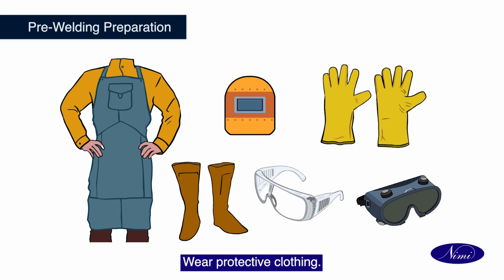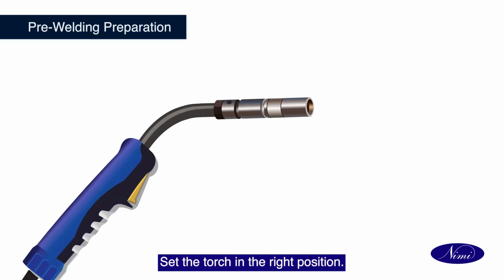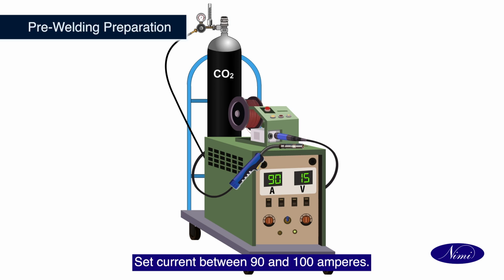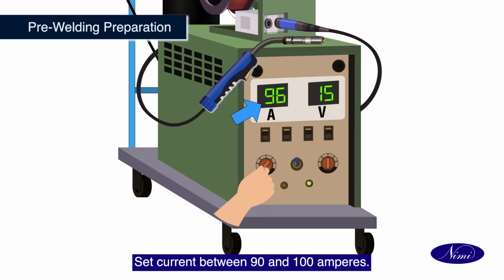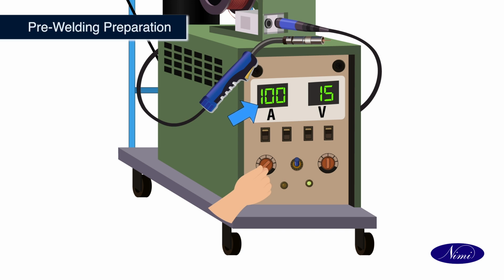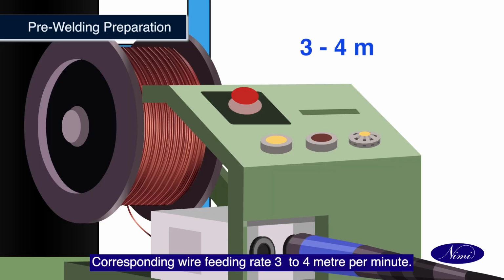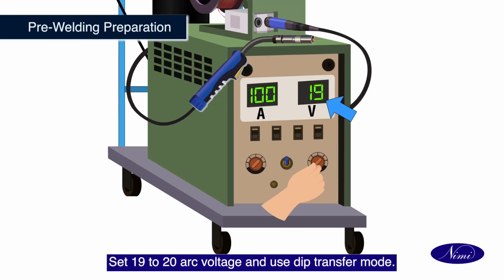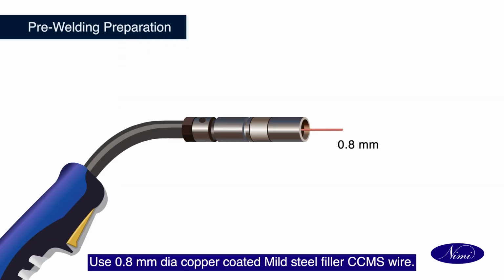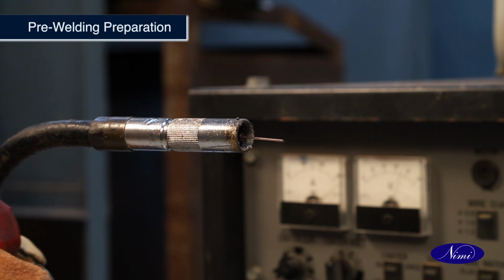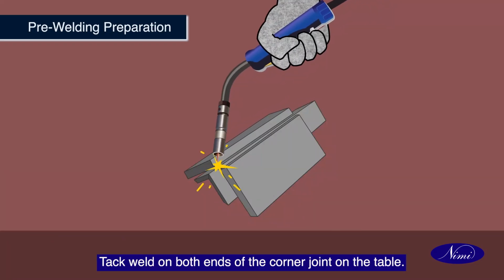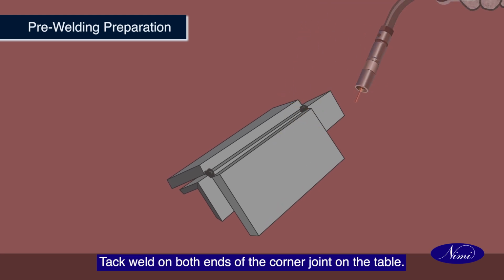Wear protective clothing. Set the torch in the right position. Set current between 90 and 100 ampere. Corresponding wire feeding rate 3 to 4 meter per minute. Set 19 to 20 arc voltage and use dip transfer mode. Use 0.8 mm dia copper coated mild steel filler CCMS wire. Tack weld on both ends of the corner joint on the table.